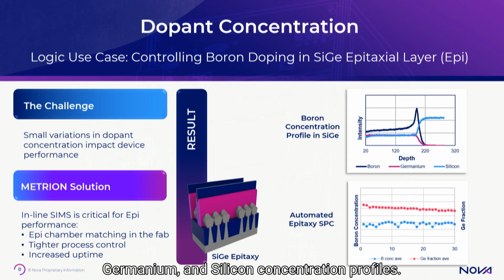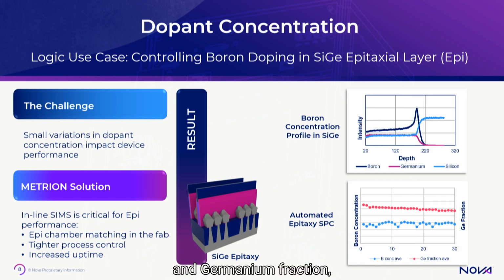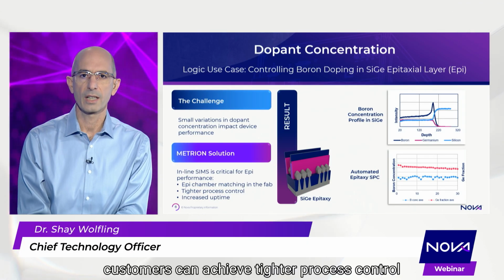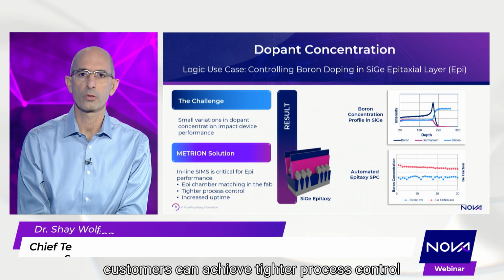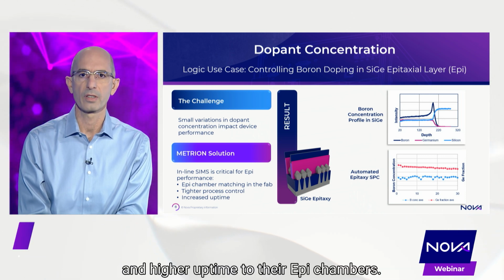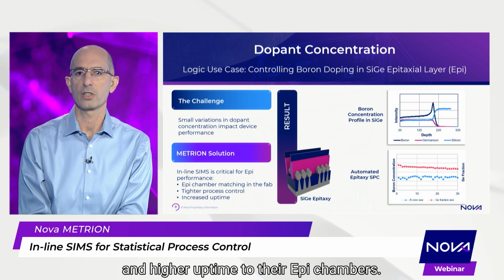and silicon concentration profile. On the bottom graph, you can see the tracking over time of the average boron concentration and the germanium fraction as being sent to the fab host for automatic SPC of the epi process. As a result of chamber qualification and matching in the fab, customers can achieve tighter process control on the challenging epi process and higher uptime of their epi chambers.